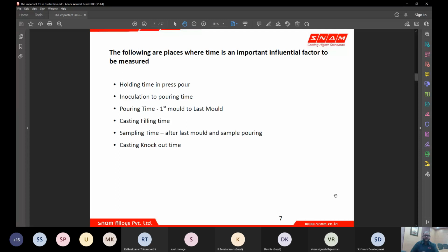And if it is manual pouring, and the pouring rate changes within a single heat, that will have a direct impact on the cooling rate of the casting, and it can affect your mechanical properties or microstructure also. We might not be able to identify, or we don't have a track of every single mold pouring time. Say, for example, you are supposed to fill a bigger mold in 20 seconds, and in a heat you might have to pour 10 boxes or 20 boxes. For every mold we do not have a time record, unless it is an automatic pouring line. So we should be able to pour at a constant, average rate.